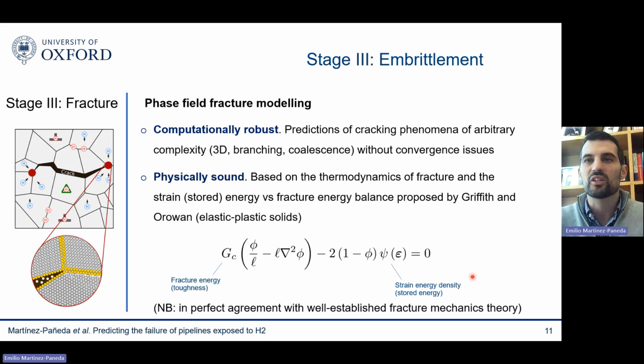So again, based on thermodynamics, on this balance between stored and fracture energy, and relying on something that we know very well, the strain energy density, which evolves with mechanical straining, and this fracture energy, that is the material toughness that we can measure in fracture experiments. And I think the good point to emphasize is what I write here: because it's based on Griffith, because it's based on the thermodynamics of fracture, it is in very good agreement with well-established fracture mechanics. So you will see that in general, whenever we have homogeneous material under certain conditions, whenever we can, we should use fracture mechanics theory. It's well established. We know that it delivers a good agreement with experiments, and it is what underpins our design codes and our standards. So it's good to have a tool that is in agreement with our standards, but that can also handle the more complicated scenarios where maybe conventional fracture mechanics or simple fracture mechanics models break down.